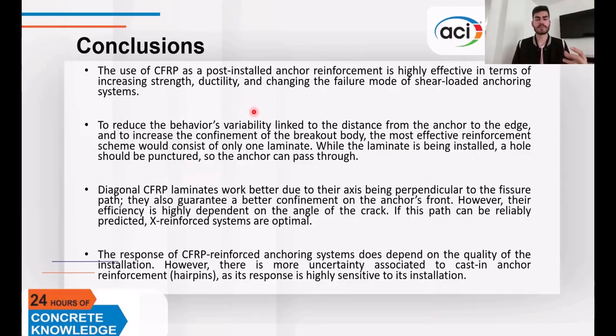These are some of the conclusions of this study. The use of CFRP as a post-installed anchor reinforcement does increase the strength and the ductility and changes the failure mode of shear-loaded anchors. To reduce the behavior's variability and to increase the confinement of the concrete, it is recommended to use one single laminate instead of distributing the area of reinforcement on various individual strips.